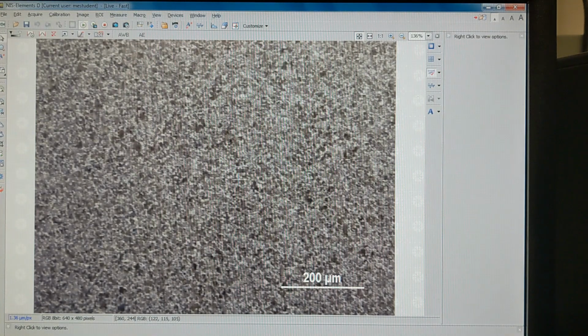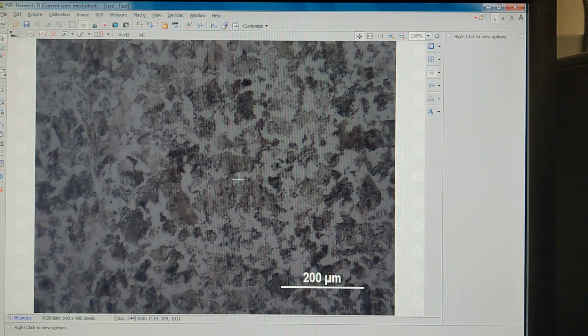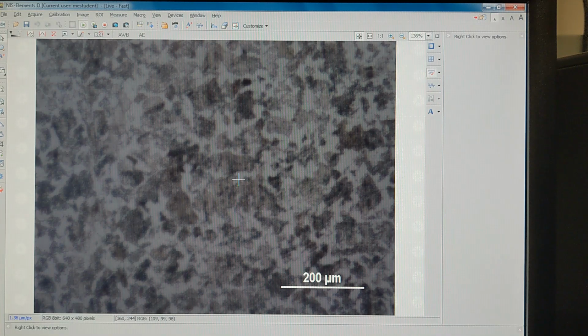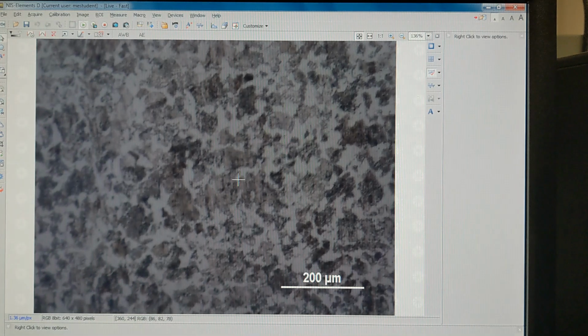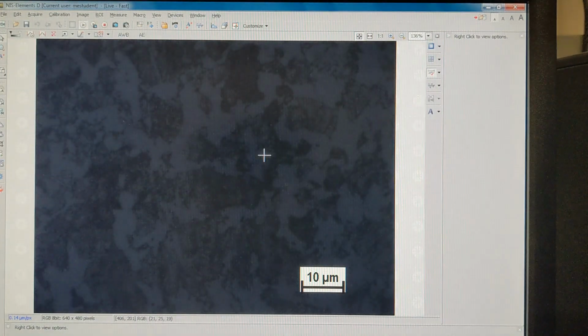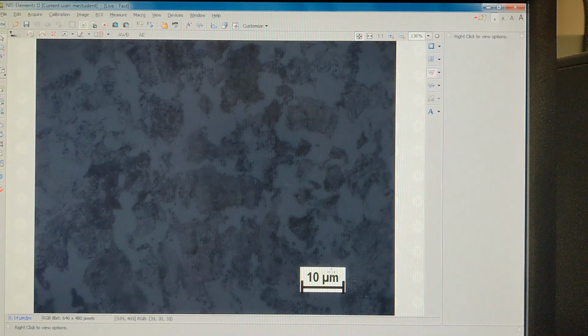Yep, all right, so this is our circular cross section. Everything looks pretty small, so let's zoom in. 20 times, 50 times. So this is our hot rolled or normalized. You can actually see our heat treatment made our average grain a little smaller. If we go back to objective, 100 times. This is as bright as it gets, unfortunately. A single region of pearlite would be a grain, and a region of ferrite would be a grain. So it looks like this ferrite grain is perhaps 15 microns across and 3 to 5 microns wide. This one is 20 across and maybe 10 wide.